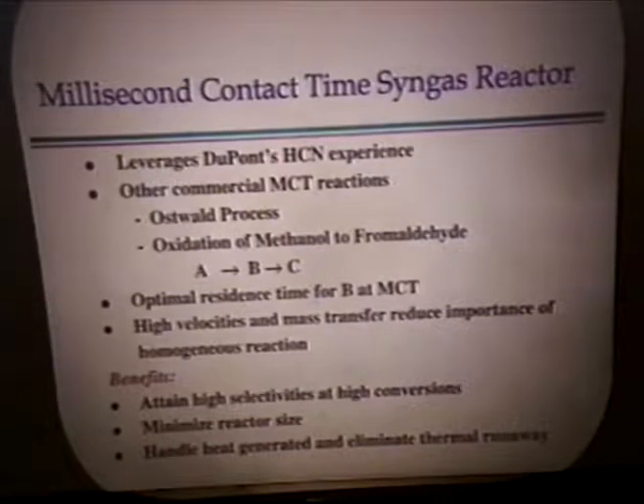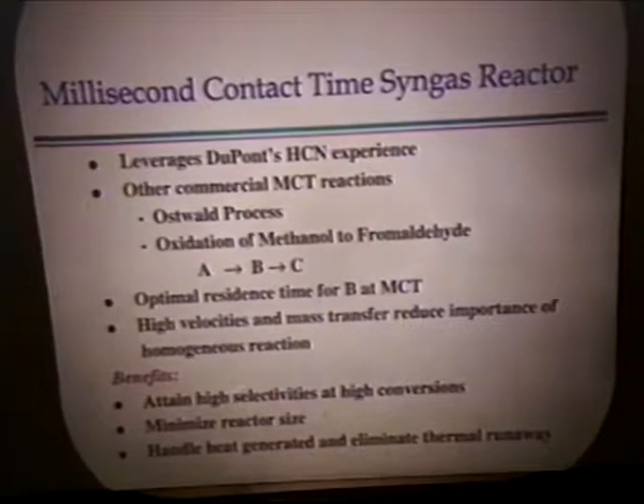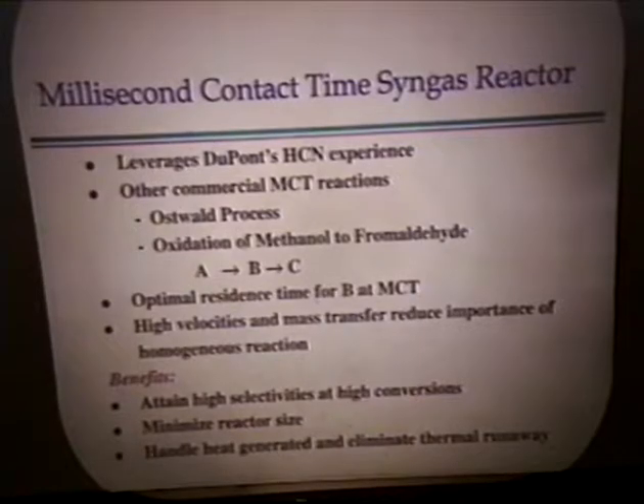So you want to have the optimal residence time and operate at high velocities. You have the benefit that mass transfer becomes less important. Also, your homogeneous reactions become less important, so you control your selectivity. So you get high conversion and high selectivity. You have a high throughput rate, which means you can minimize your reactor size. And from an engineering standpoint, you can handle the heat generated and eliminate thermal runaways.